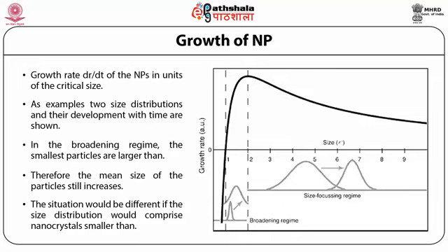If all the crystals present in the solution have a radius larger than this value, the smallest crystals grow fastest, and therefore the size distribution becomes narrower over time. The value of r star depends mainly on the overall concentration of free monomers, but also on the reaction temperature and on the surface tension σ.